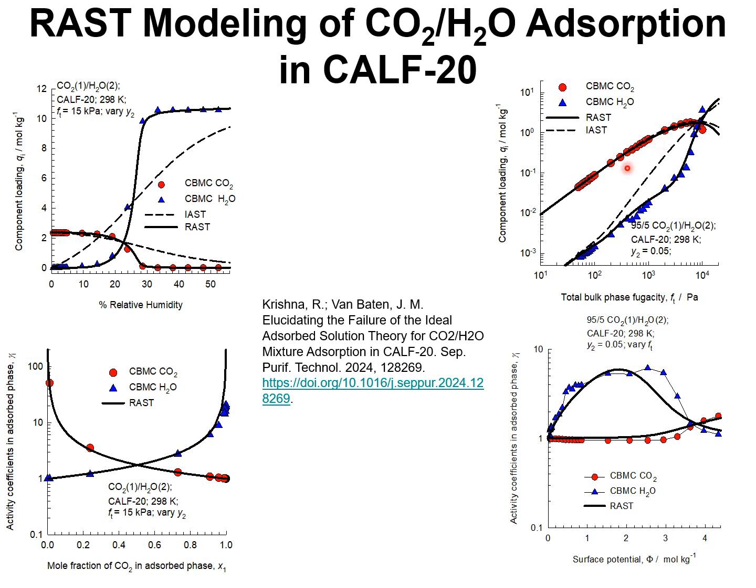From the CBMC data, the activity coefficients in the adsorbed phase mixture can be backed out, as explained in this article of mine. For the two sets of CBMC simulations, the adsorbed phase activity coefficients are shown in this diagram on the left for this CBMC data set, where the activity coefficients are plotted as a function of the mole fraction of CO2 in the adsorbed phase.